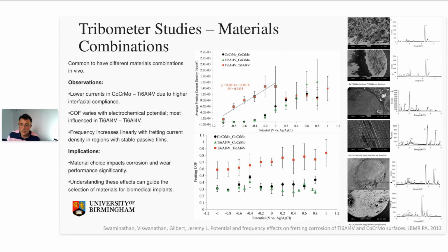But ultimately, what has been noticed is that they play a significant role in terms of the actual fretting corrosion mechanisms, where Gilbert and Swaminathan have proposed that things like cobalt alloys with a titanium contact can dominate the tribological performance, but titanium interactions are very much more susceptible to the chemical component of deterioration.